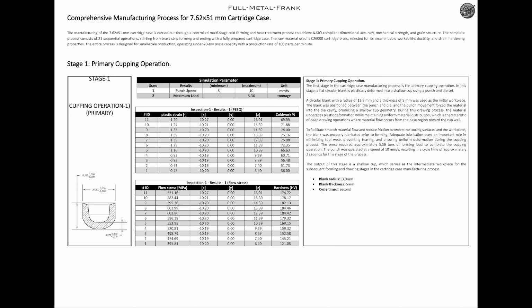Stage 1. Primary cupping operation. The first stage in the cartridge case manufacturing process is the primary cupping operation. In this stage, a flat circular blank is plastically deformed into a shallow cup using a punch and die set. A circular blank with a radius of 13.9 millimeters and a thickness of 5 millimeters was used as the initial workpiece. The blank was positioned between the punch and die, and the punch movement forced the material into the die cavity, producing a shallow cup geometry.